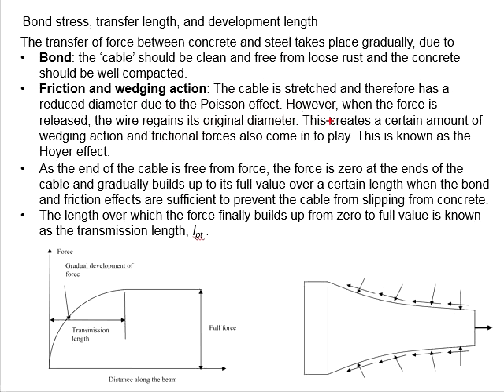This is known as the Hoyer effect. These frictional and wedging actions lead to some losses in stressing, where the tendon requires a certain transmission length for the full pre-stressing force to build up.